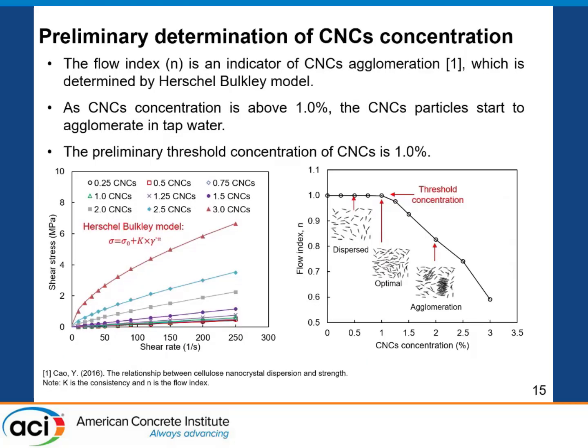So now we know that the CNC can be well coated on the surface of the steel fibers. The next question for us is, how can we determine the concentration of the CNCs? What concentration should we use to coat the steel fibers? So here we conducted the rheology test. We used an Anton Paar rheometer and measured the mixtures with different concentrations of CNCs, measuring the shear stress and shear rate flow curves. We used the Herschel-Bulkley model to fit these curves and get a flow index n here. The flow index can be used as an indicator of the CNC's agglomerations.